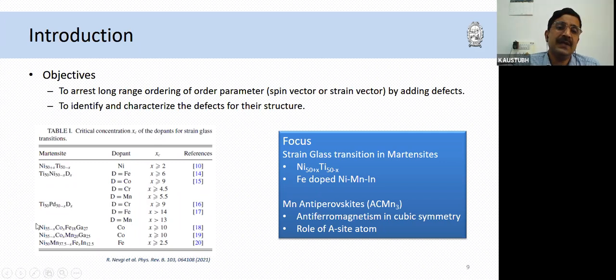The motivation for this work came from the work of Xiaobing Ren at NIMS, wherein, for example, they took nickel titanium, which is a well-known martensite, nickel 50, titanium 50, and they doped it with different impurities. And almost every time, above a critical concentration of this doping of impurity, the martensitic behavior changed to strain glass behavior. So the two things that we noticed were that the concentration of defects was very small, and that the strain glass state was almost a universal state when you dope a martensite with defects.